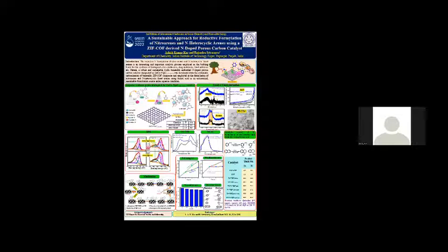The obtained catalyst was systematically characterized by various characterization techniques that include powder XRD, BET, Raman, and HRTEM. BET tells about the surface area where the maximum active sites are distributed, and Raman tells about the kind of carbon material or the carbon structure present. So definitely you can see here the effect of adding the COF. Herein I have just a comparison of the two catalysts I'm talking about. One is with COF and another one is without COF.